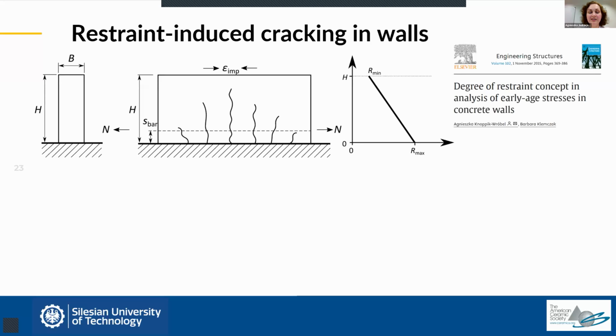But anyway, as I have shown in the slide before, we may say that in the central part of this wall, the tensile stresses, so when we have this imposed deformation that is negative, which means it's trying to shrink the wall, and as a result, there is a tensile force that develops. So even though this tensile force is eccentric, we can say that in the central part, it produces pure tension. And since the design for cracking is focused on the maximum crack width, and the maximum crack width will appear in the center, we can simplify such a wall into a tie.